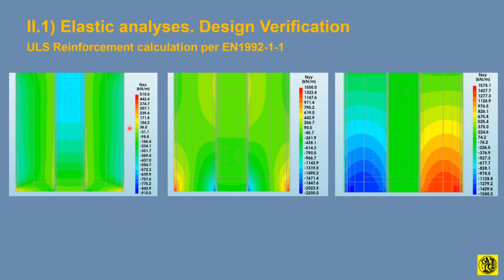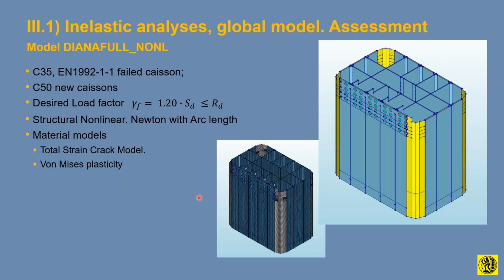In the x direction, there's very, very little, actually, because it's a very high wall, but the vertical forces are fairly high in these corners here. And then there is a constant shear practically over about a half length, which gives us a sandwich model, in this case here, of some horizontal and vertical reinforcement. But this was not the case in elastic analysis. Okay, so let's look at the inelastic analysis now.